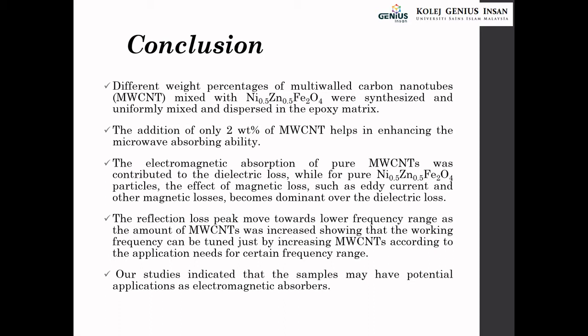The electromagnetic absorption of pure MWCNT was contributed by the dielectric loss, while for pure nickel zinc ferrite particles, the effect of magnetic loss, such as eddy current and other magnetic losses, becomes dominant over the dielectric loss. The reflection loss peak moved towards a lower frequency range as the amount of MWCNT was increased, showing that the working frequency can be tuned just by increasing MWCNTs according to the application needs for a certain frequency range. Our studies indicate that the samples may have potential applications as electromagnetic absorbing materials.